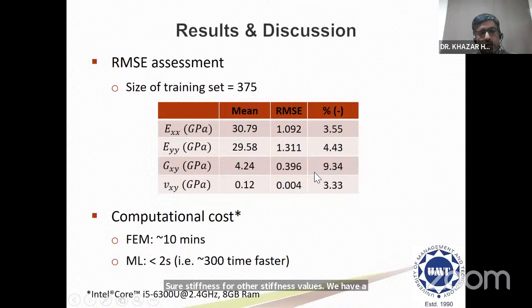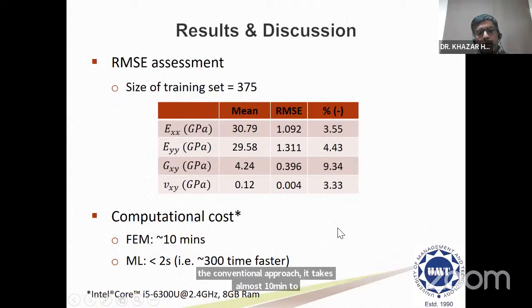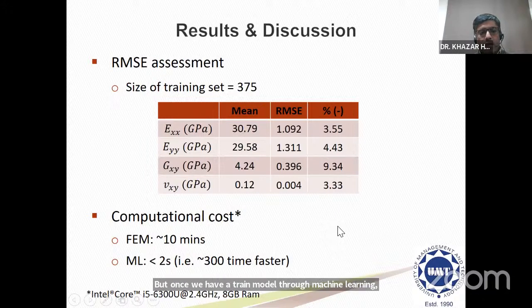And in terms of computational cost, if we compare the results, you can see that if we perform finite element simulation, which is the conventional approach, it takes almost 10 minutes to estimate these 4 elastic properties. But once we have a trained model through machine learning techniques, it takes less than 2 seconds. So the processing time is almost 300 times faster.